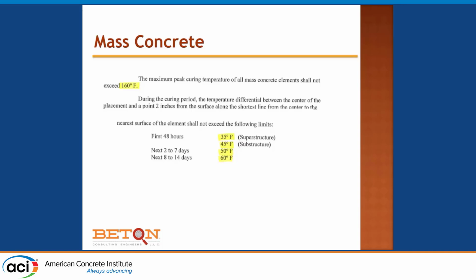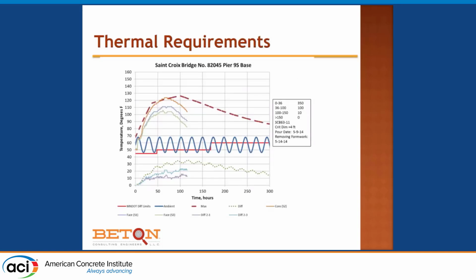And we have some requirements for mass concrete, mass elements. We have built this performance-based approach. This is work we've done with MnDOT, that we can handle much higher temperature differentials as our strength goes up. And even though I doubt there's enough ettringite in there to make any kind of problem, even if it was delayed, at a very small cement content, we are going to not exceed 160 degrees, because, as we saw in the picture, we are building them up above the river.